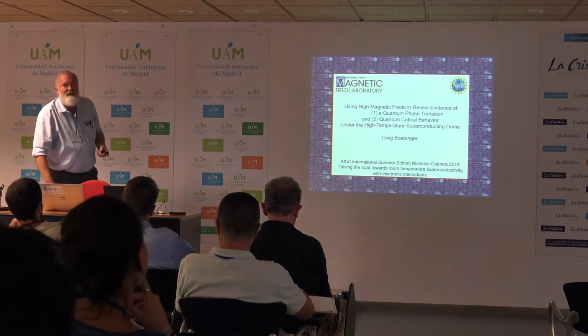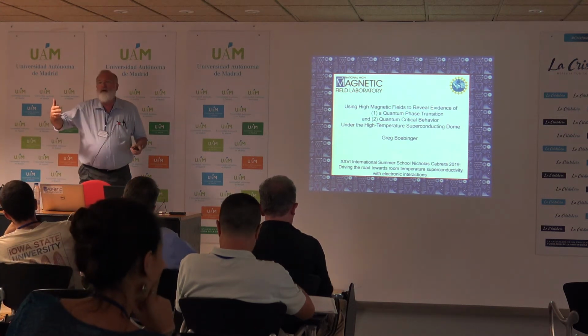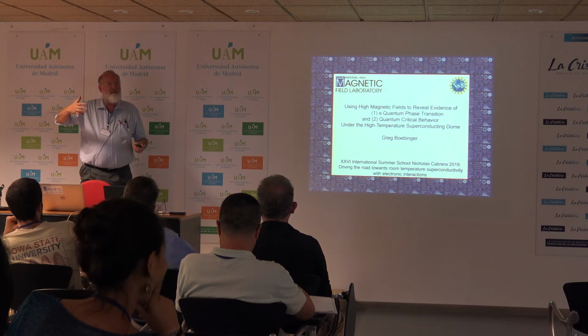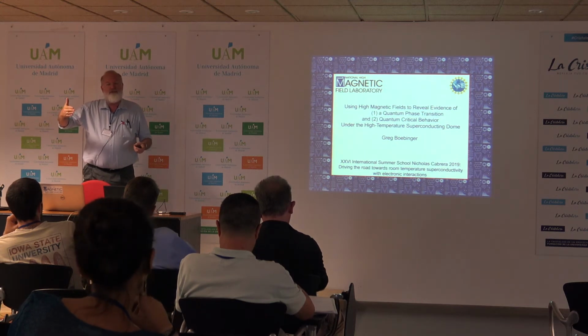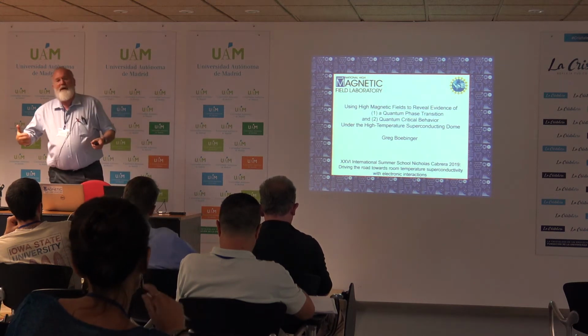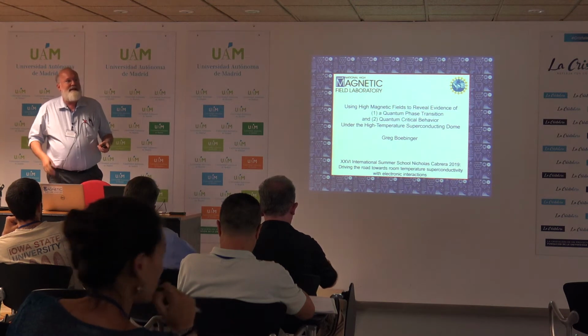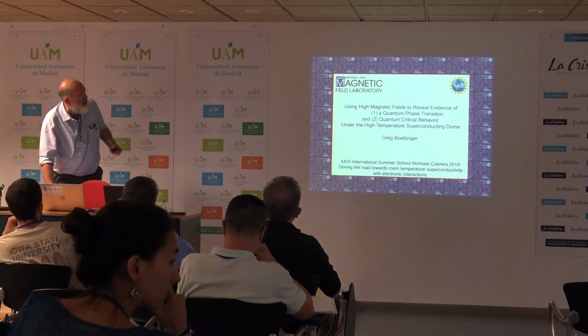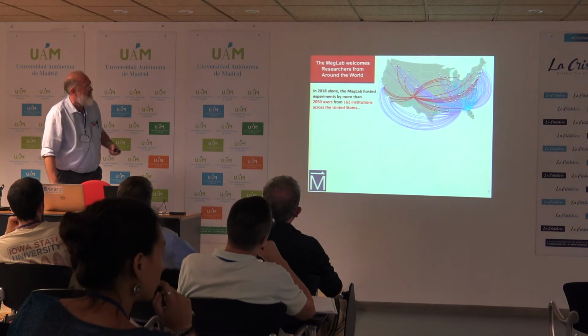And even with the highest fields of now 90 Tesla and above, we can only suppress the superconducting dome to zero temperature in the least competent of the cuprates, as well as the nickelate superconductors. But YBCO, we can only suppress down to about 50 Kelvin.